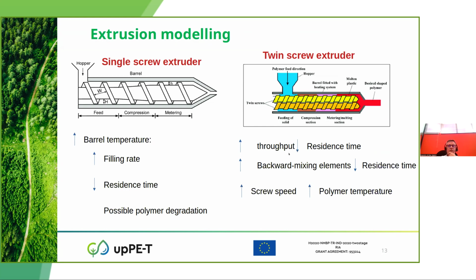The main effect on the melt temperature comes from the screw speed and feed rate. That means that a higher melt temperature is measured due to mechanical energy input in the mixing zones at higher screw speeds.